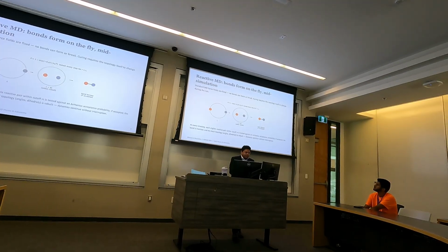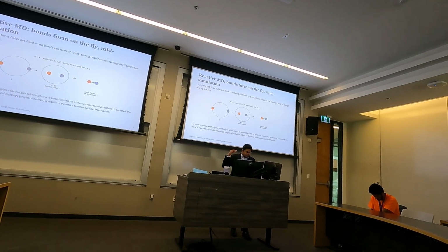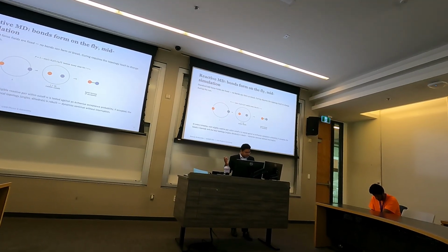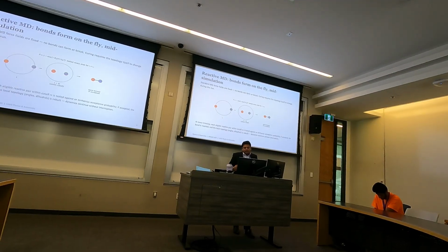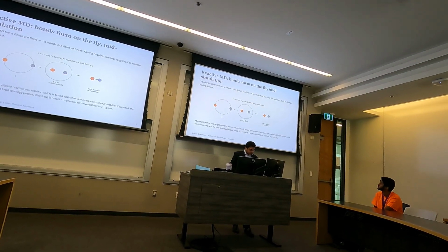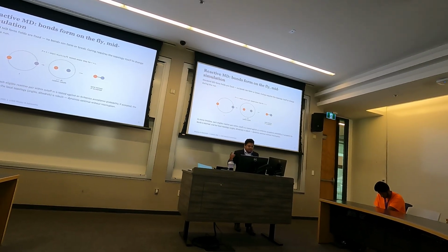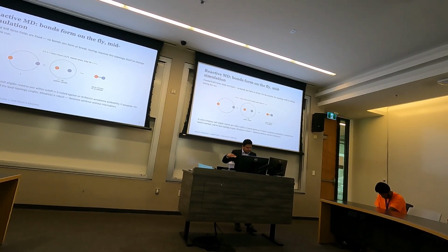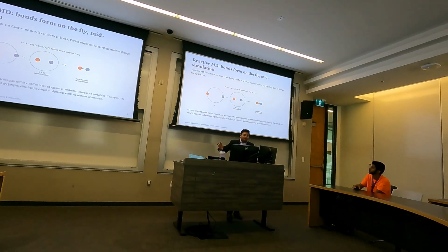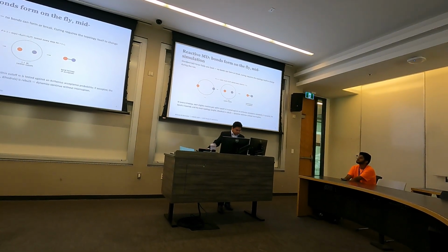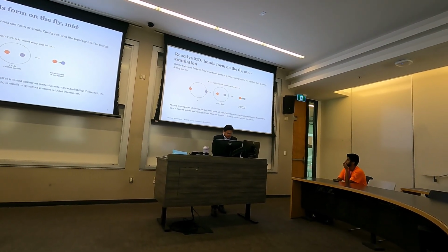We look at the nearby reactive pairs at every time step, and then we calculate the probability, which is based on the distance and the temperature. If the pair passes the test, you form a bond, otherwise you don't. This topology is updated in real time, so all the angles and the dihedrals are also updated as the reaction goes on. The parameters for these angles and dihedrals come from the COMPASS parameters in LAMMPS. LAMMPS is the simulator that we are using in this case.